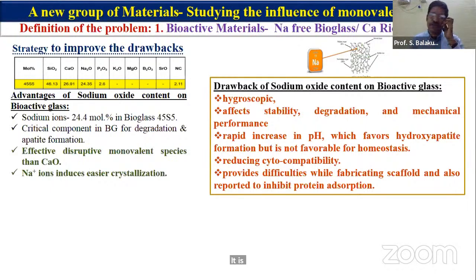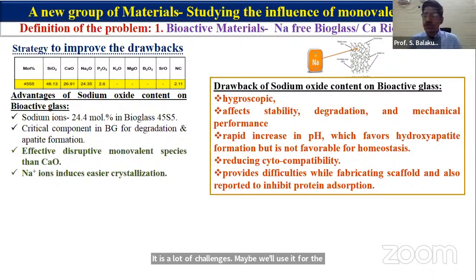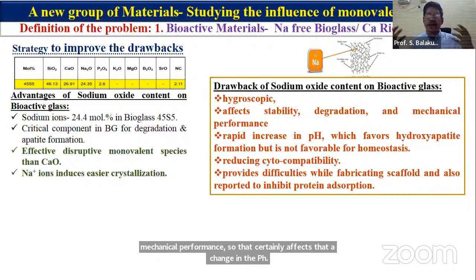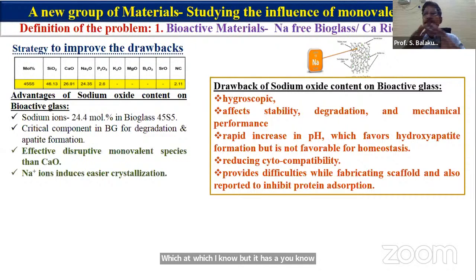Maybe it will be useful for the students that I listed some of them. Sodium introduces high hygroscopicity, and also affects the stability, degradation, and mechanical performance. That certainly changes the pH, which is favorable for hydroxyapatite formation, but not favorable for some applications, though good for hemostasis. But it is also reducing the cytocompatibility, producing difficulties when fabricating scaffolds.